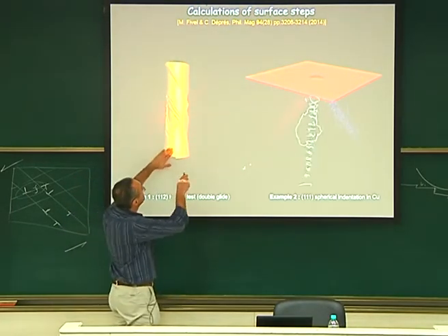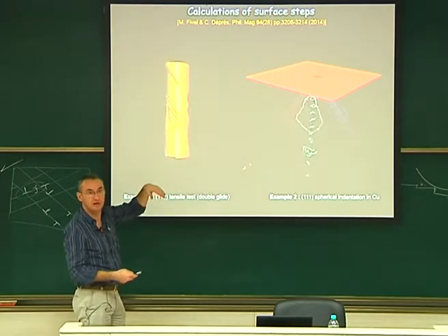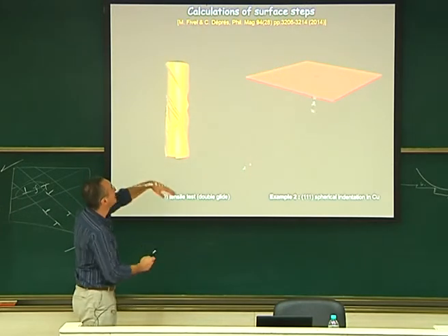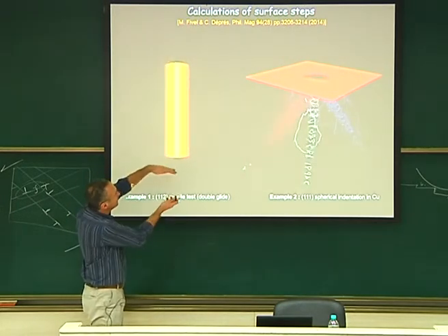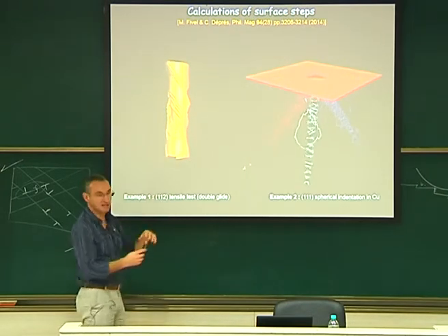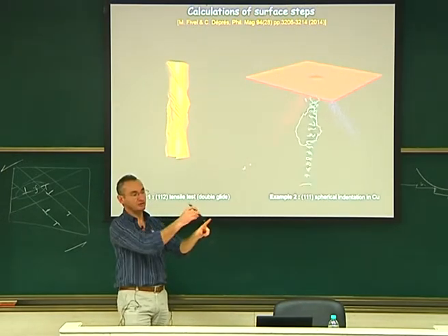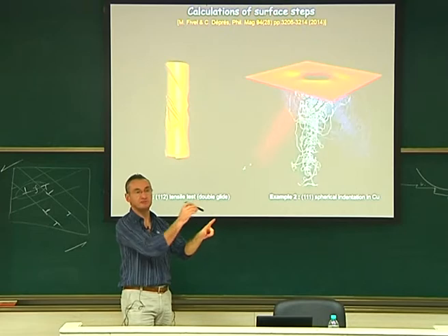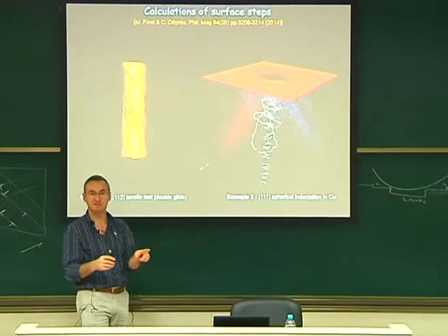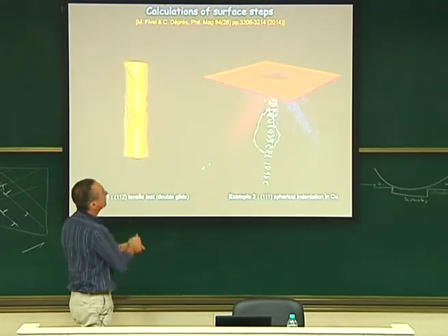This was to answer a question we had yesterday. Here, if I put two slip systems which are equivalently loaded, which we call a double glide configuration, you have the same shear on the two slip systems. You can see that by summation of the two shears, you can accommodate some tension. It is a highly symmetric condition. It's like if I was loading on my standard triangle on the axis between B4 and C3. Remember yesterday? If I just pull between the two, so the two systems are active the same way, then they behave like that. You have two shears, and this way you can accommodate tension.